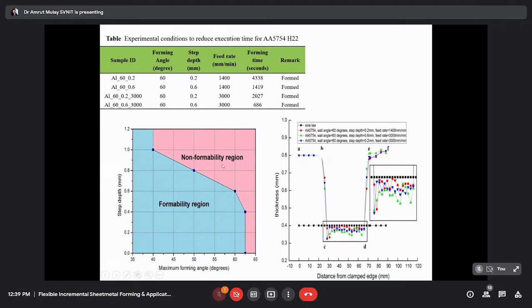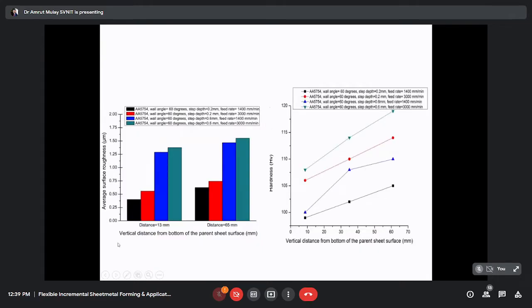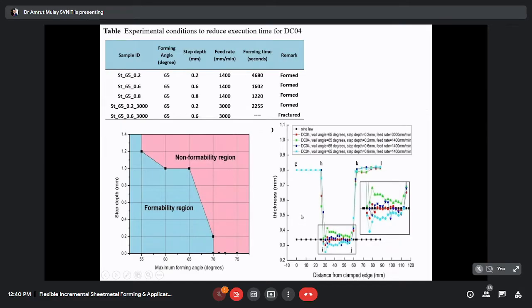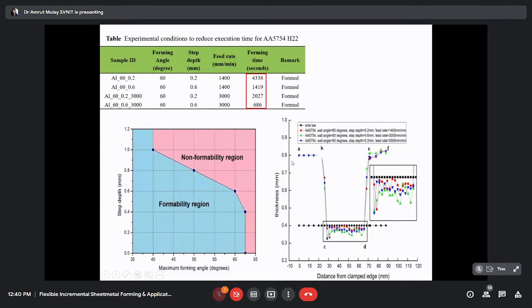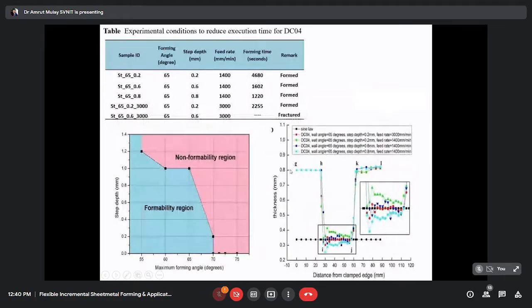In all the possibilities we had, we extended our limits, and we found that the machining time was reduced from 4338 seconds to 686, and the part is formed. We compare those parts, and you can see the comparison in terms of surface roughness and in terms of hardness, that is nothing but material characterization. It is material characterization, right? And again you can see that I think this is for 5754. Now the study is extended for DC04.